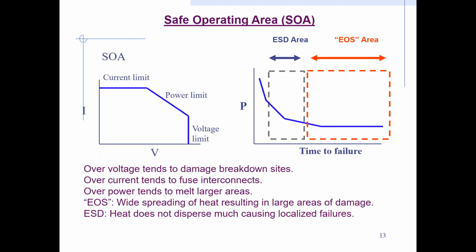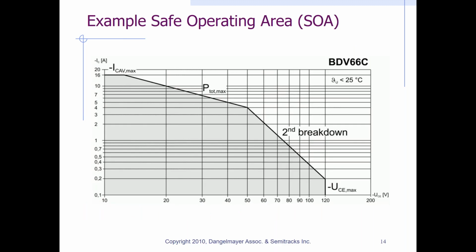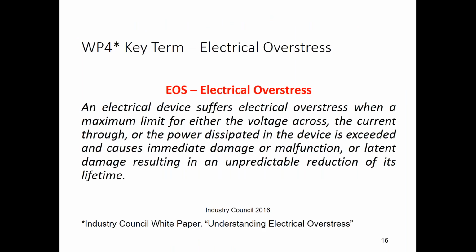Oh, so a voltage stress can cause a high electric field at some point in an object. And so the driving force becomes that field. Whereas a current can flow in a metal line, for instance, and cause heating. So that's what we're talking about there. So one is exceeding a breakdown limit, having to do with an electric field, which is caused by a voltage, and a current flowing where the degradation of the device has to do with Joule heating, just the material heating up above some limit. Okay. All right, we can go on to 16.